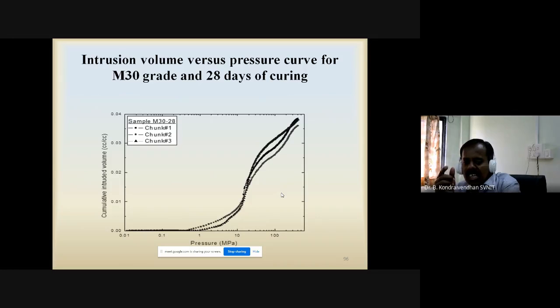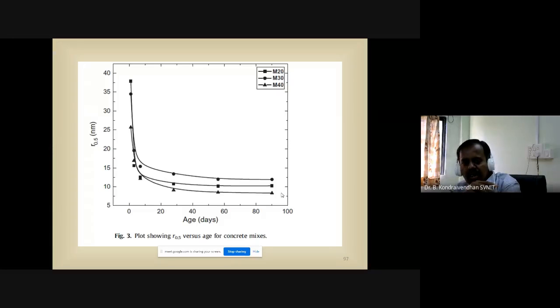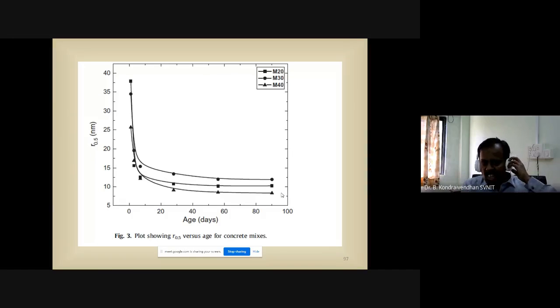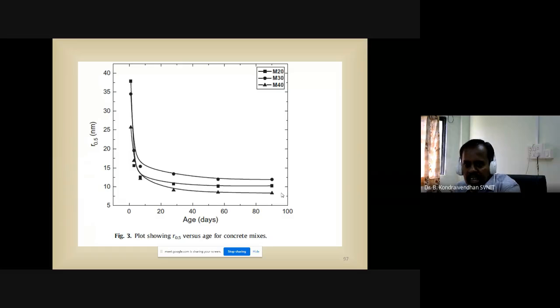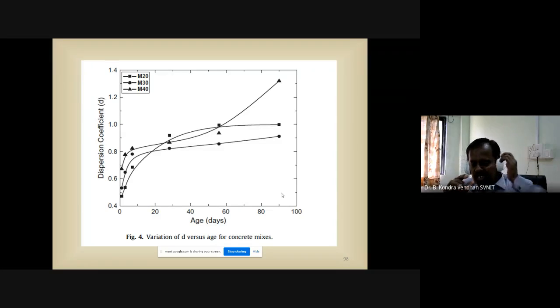Okay, so he calculated this kind of curve, and he got it for M30, M40 grades also. So this is the accumulated intrusion volume versus pressure curve. This is only experimental work he has done. Then he has plotted the mean distribution radius versus age, for M20, M30 and M40 grades. Then the dispersion coefficient he also calculated for all three grades, and plotted the dispersion coefficient versus age.